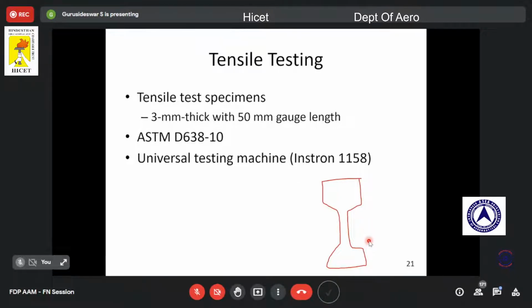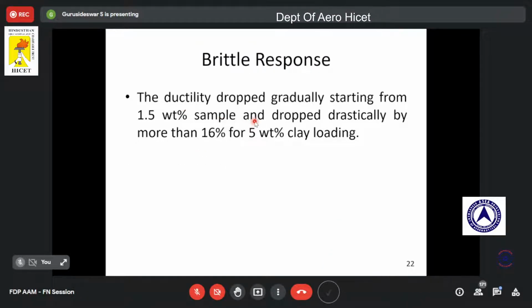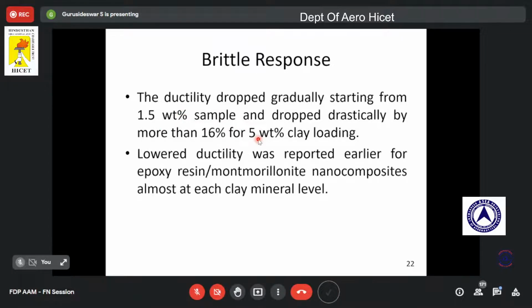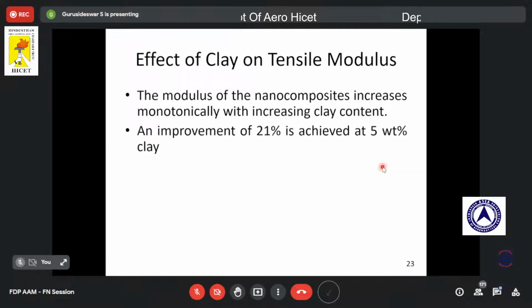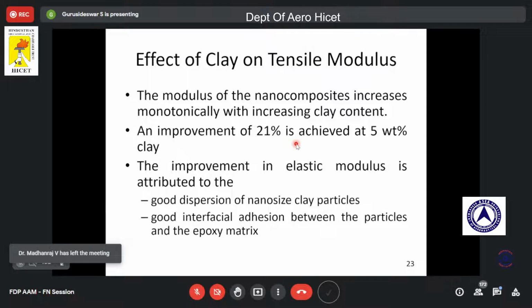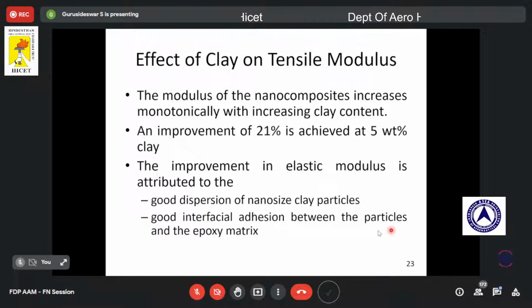So this has the ASTM standard D638, and this is the response we get from the tensile testing. As clay is a brittle material, when we disperse clay with epoxy, we expect a drop in the ductility. This is what we observe, and the same observation was made by many researchers. And here I have presented the effect of clay on tensile modulus. The addition of clay in epoxy leads to good improvement in the tensile modulus because of its good dispersion and because of its good interfacial adhesion between the nanoparticles and the epoxy matrix.